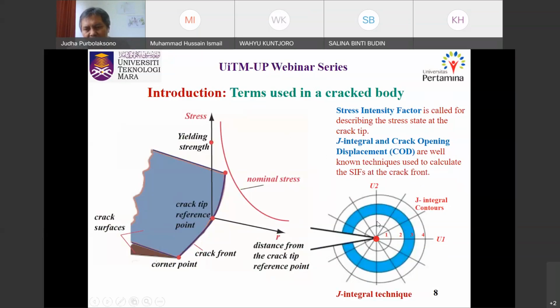So the lower one here is what we call the J integral. In this work we are actually using the J integral. Basically, if we take the reference point here as the crack tip, then we have a number of contours. We utilize the data from displacement and also strain and put it in the formulation. The idea comes from the strain energy release rate, which is then converted into the stress intensity factor.